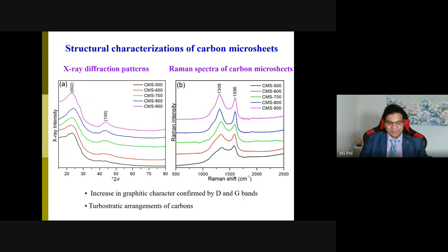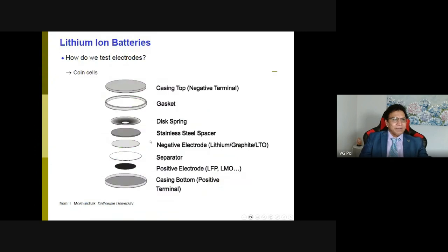We can also use the X-ray to check and probe the materials and check their purity. Here, the X-ray demonstrates that this is a carbonaceous material prepared at various temperatures in order to optimize the best temperature to get this carbon from packing peanut. Once we have the material, we wanted to make the batteries.